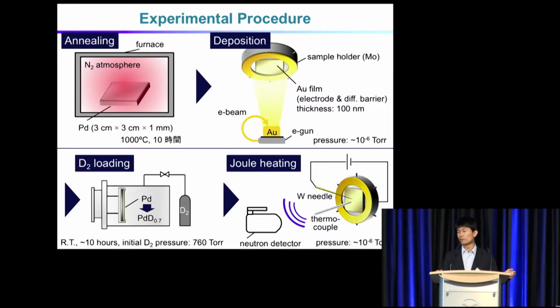And then we loaded deuterium gas into the palladium sample at room temperature and atmospheric pressure. And then Joule heated to stimulate the reaction with a tungsten probe or electrical needle attached to the sample to make a current injection through the sample.